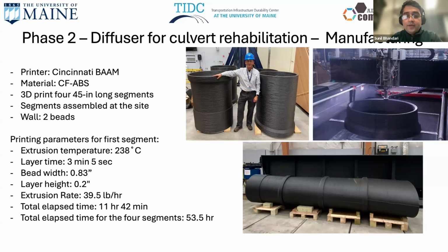It wasn't feasible to print the whole part at once because it's long. Because of the height restrictions, we printed the part in 4 different segments, one part at a time. And the segments were assembled at site. We transported them to site, and New Hampshire DOT employed a contractor to assemble it. The printing parameters for the first segment were: the polymer was extruded at a temperature of 238 degrees Celsius. The layer time for that part was 3 minutes 5 seconds, and bead width was 0.83 inch.